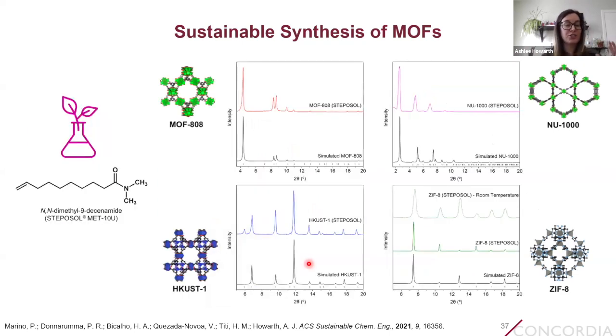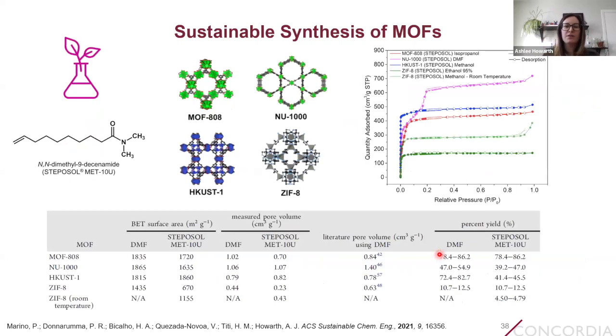And so Paula showed that she could indeed replace the DMF in the synthesis of all 4 of these MOFs with Steposol simply by using the same number of milliliters of Steposol in place of DMF. And so these are just the powder X-ray diffraction patterns showing that all the materials were synthesized and that they're crystalline and phase pure. We can also see that whether the MOF is synthesized in DMF or Steposol, it has very similar properties, so that it can still be activated, it still has permanent porosity, the BET surface areas and pore volumes are quite comparable, and the percent yields are comparable as well.